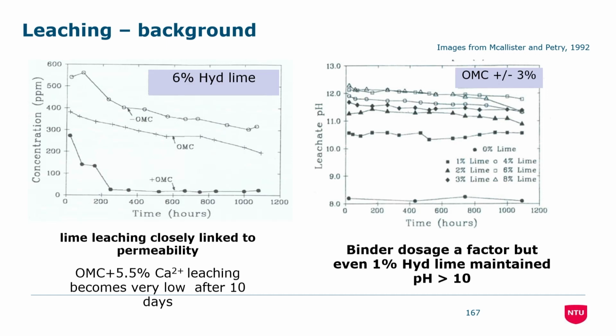We can also link that into some direct leaching studies. These are studies where they've set up leaching cells and forced water through a treated material to see what would happen over time. In this study, they undertook continuous leaching for up to 90 days or 45 days, depending on the variant. On the left side here, we've got quite a high dosage of binder, so 6% hydrated lime, which is about 4% quicklime equivalent. One thing we can see is, on the y-axis, we've got the concentration of calcium in parts per million, and then the time leached. And we can see a difference between the dry of optimum moisture content